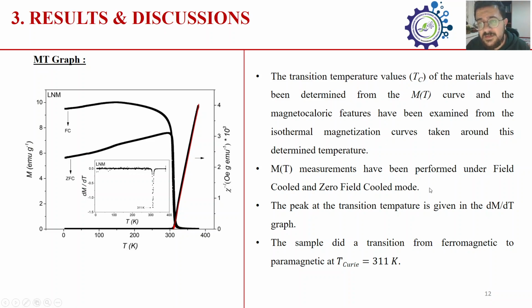The transition temperature values, the Curie temperature of the materials, have been determined from the MT curve, and the magnetocaloric features have been examined from the isothermal magnetization curves taken around this determined temperature. The peak at the transition temperature is given in the derivative MT. The sample showed a transition from ferromagnetic to paramagnetic at the Curie temperature.